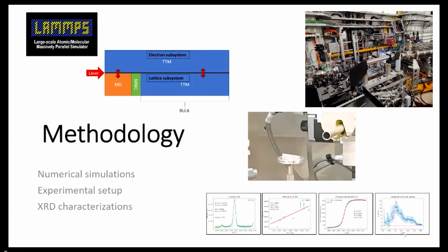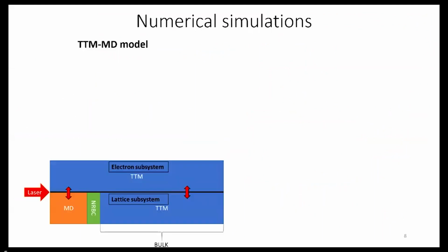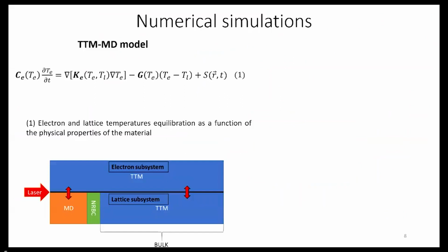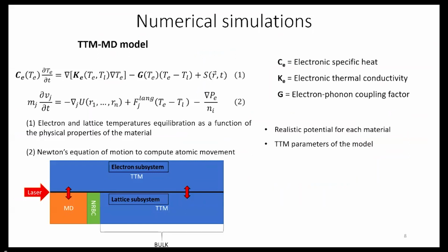So let me present the methodology, first with the numerical simulations. We are using a combined model of two-temperature model and molecular dynamics. It consists in making two subsystems of the material, one for the electronic part and one for the atoms, the ions. To simulate the laser on the material, we are using the two-temperature model, which creates a source from the gradient of the electronic temperatures, and which is linked to the other subsystem thanks to Newton's equation of motion to compute the movements of the atoms during the peening.